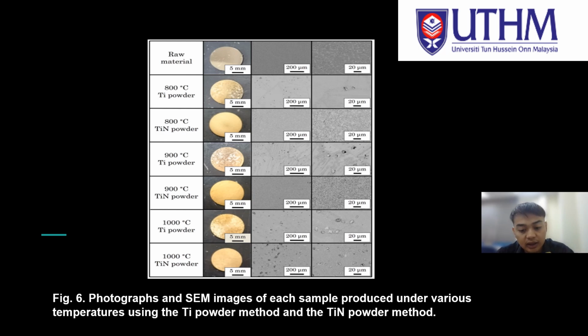In both mechanisms, it is considered that the TiN coating progressed excessively due to the thermal runaway. In other words, in the Ti powder method, excessive coating progress results in the problem of a rough coating film. In the case of TiN, thermal runaway was suppressed around the substrate. From this result, the TiN powder method at 900 degrees Celsius resulted in the fabrication of the sample with the highest hardness and the lowest roughness.